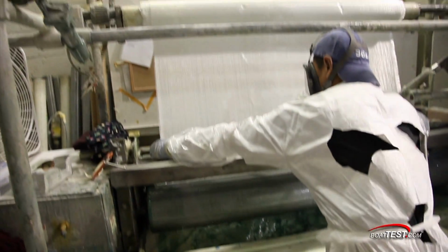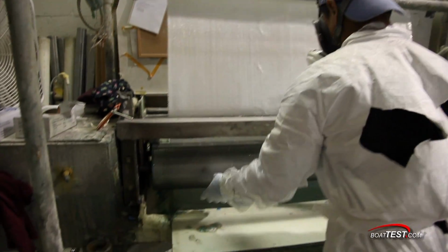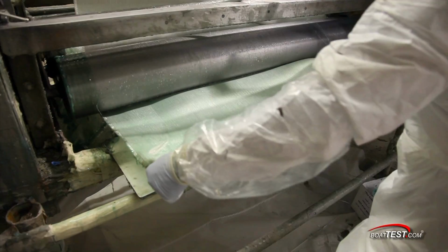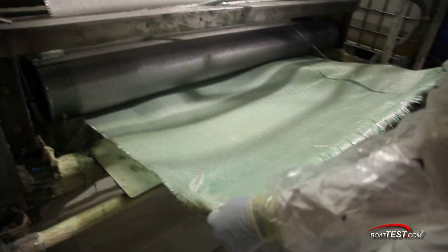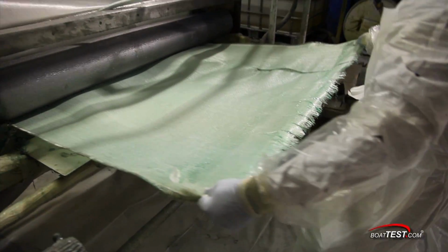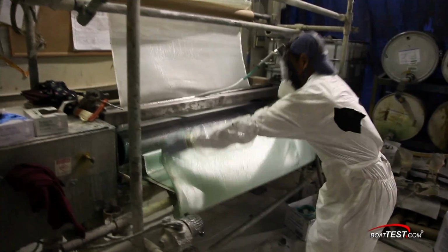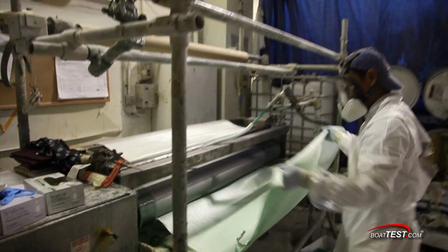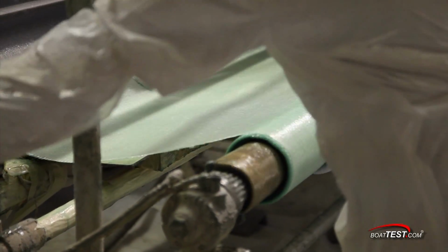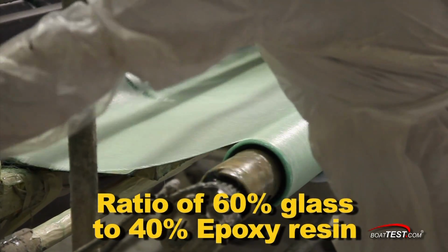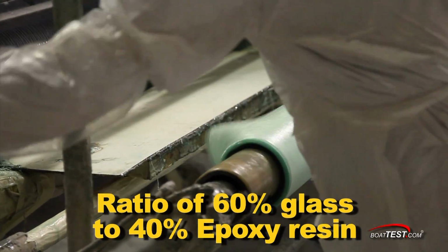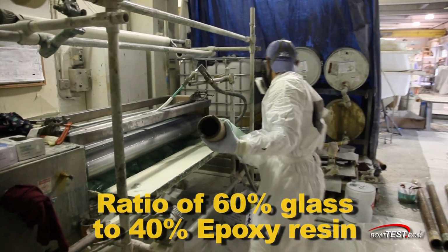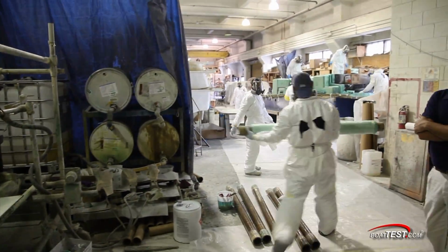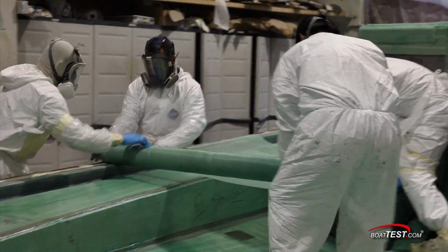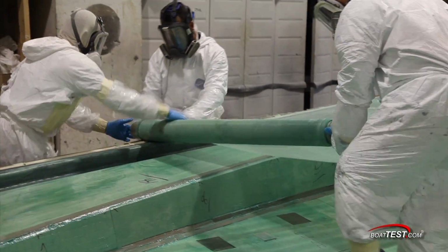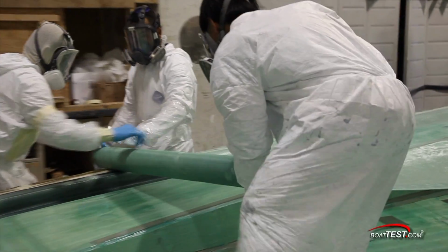Here you can see the process, which utilizes a specialized machine. The fabric is fed through a bath of epoxy, then between rollers which control the ratio of resin. It is important to note that the ratio of resin to the glass fabric by weight is exactly 60 to 40, 60% glass weight to 40% resin. This is important because the strength comes from the glass. Here you can see how the resin impregnated bi-glass is then applied to the foam core structure, with the main strands running bow to stern.